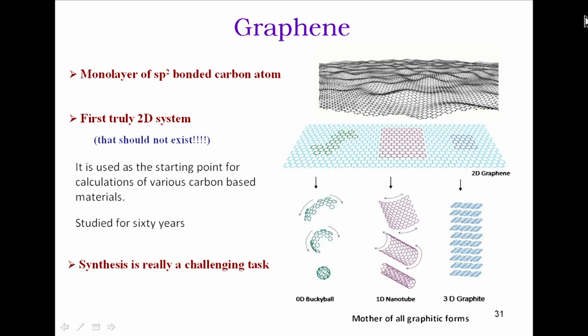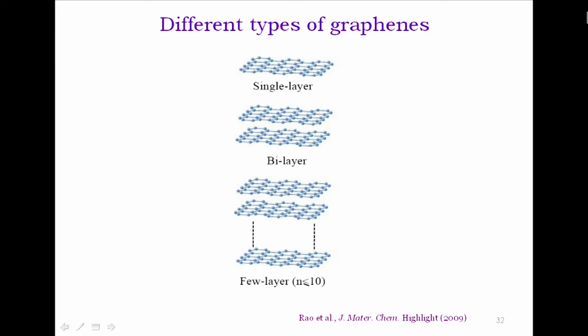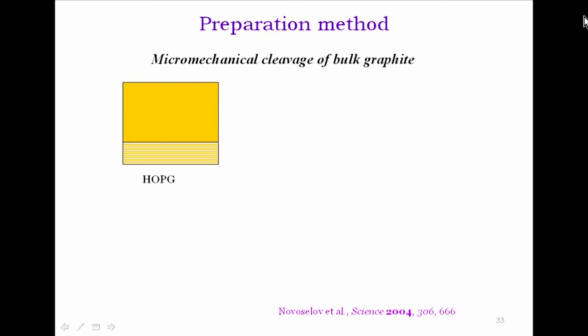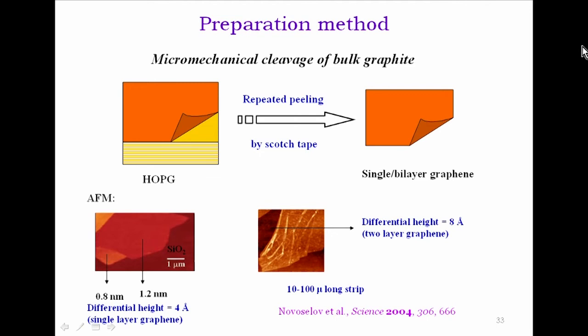How do you make it? But they were not succeeding in making it until, of course, recently, about 5, 6, 7 years ago, when these two Russian friends in Manchester did this. See, in graphene you have a single layer, you can put 2, you can call it a bilayer, you can have a few layer graphene. Well, less than 10; if you have more than 10, it's more like graphite. So you can have all these graphenes. So what they did was, you take a single crystal of graphite, take a scotch tape, and peel off the top layer. Of course, someone like me would put a lot of pressure on the graphite and get many layers off. They delicately touch it to get one layer sticking to the scotch tape. And you study that single layer, and you measure the height of that. It may have 2 layers, a single layer, and you can do microscopy of various kinds on that.